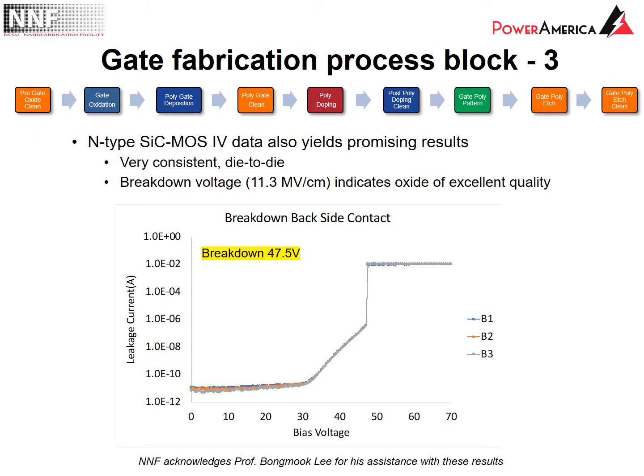We also took the silicon carbide MOS device and measured some IV data and wanted to look at the oxide breakdown. And once again, we got very, very consistent results, which is key for this type of project. And the breakdown field at 11.3 megavolts per centimeter is an excellent number. It indicates we have an oxide of excellent quality on our silicon carbide.